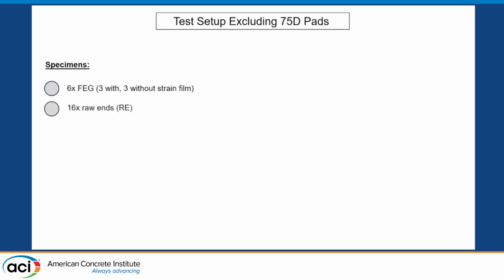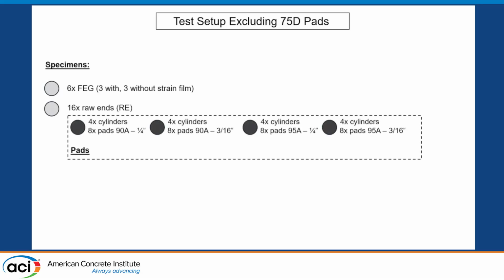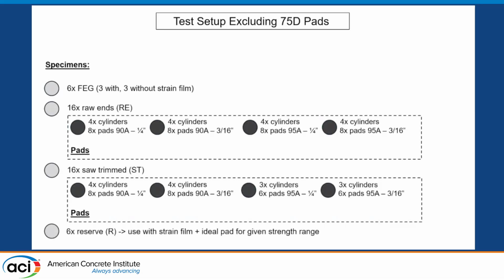But what we found is that the 75D pads were severely underestimating the fixed and ground results. So this resulted in us changing our test matrix, and so we were able to have about 4 cylinders per test later on. I'll speak on this more though.